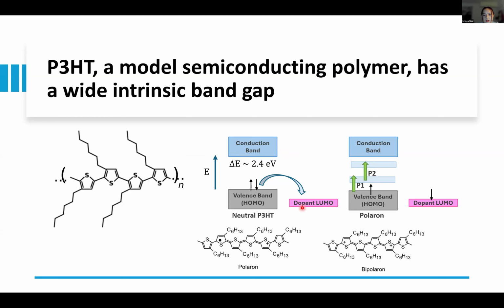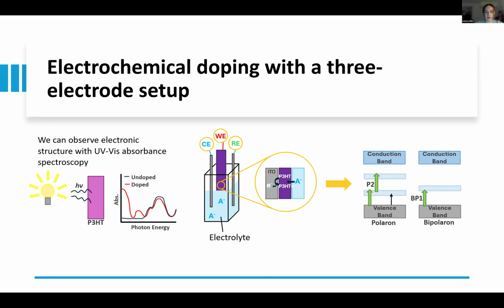So we can do this with an oxidizing molecule, like in this case, or like what we're interested in is something that is more highly tunable, which is electrochemical doping. So I'll show you how we do that. We can do that with the flooded cell, which is the diagram right here in the middle. And here we have the working electrode as our polymer, which has been spin coated on an indium tin oxide substrate. And there are two wires as the reference and counter electrodes.